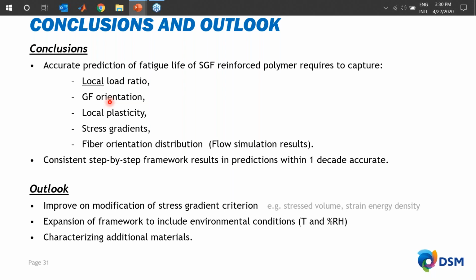Okay, thanks. Another question here. In applications, the frequencies can be very high, for example caused by vibrations, and the loading conditions are seldom with a constant amplitude. Does this work still apply for those cases, and if so, how? Yeah, that's usually a challenging one, because the problem is if you test material characterization at these high frequencies, you usually end up with too much heating. So that means that the material performance that you characterize is not representative for isothermal behavior, but is simply affected by how much heat you generate because of the cyclic load that you apply. So that's why we really focus on generating isothermal fatigue curves that allow us to extrapolate with confidence to a higher number of cycles that are more relevant for the high cycle fatigue and, for example, resonance mode.